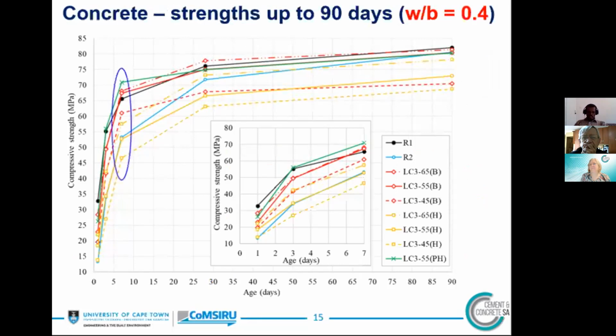You can see here at 7 days, although PH clay has low kaolinite content compared to B clay, the 55 mix with PH clay has the highest strength, followed by the 55 mix with B clay and the 65 mix with B clay, and then the reference mix R1. Here it's mainly because the PH clay has a higher internal surface area than B and H clay, so it absorbs some of the available water, therefore reducing the effective water.